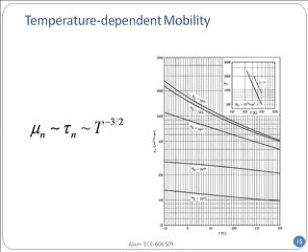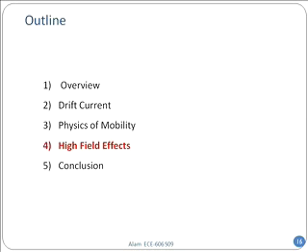And you can see in the inset that the exact experimental value is not minus 3/2. Minus 3/2 comes from theory. But if you look at the inset in the figure, in a log-log plot, it shows T to the power minus 2.3. So experimentally, it's a little bit more. Lots of people work on why it's different, but that's a separate story.